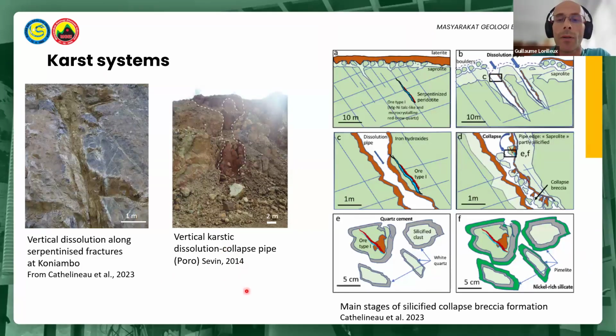Endokarst features like subvertical dissolution pipes, locally containing collapsed breccias, developed preferentially along pre-existing serpentine faults and have been described in several deposits in New Caledonia. Local collapse of the pipes by gravity collapse formed breccias cemented by quartz as well as nickel-rich talc-like garnierite on the rim of clasts, as you can see here on this drawing, related to evaporation during drier climatic episodes.